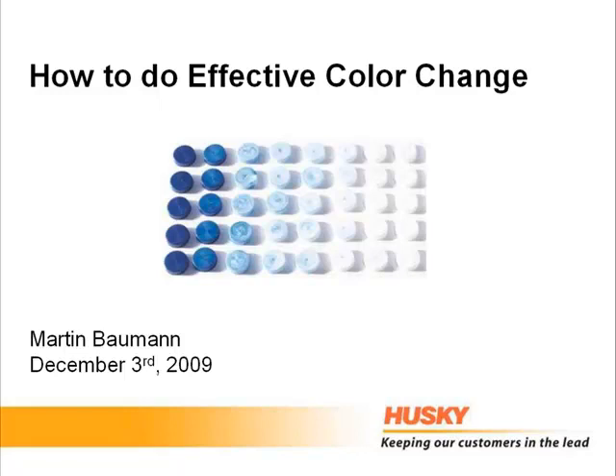One of the questions is actually if there's a difference in pressure drop with that mixing tip or the Ultraflow and a conventional tip, and the answer is it depends on the resin. Typically with polyolefins we haven't really seen it. We're now in our second generation with that mixing tip. We haven't seen a lot of pressure drop, but depending on the specific processing setup and the specific resin you use, it's always a good thing to check back with Husky if we actually foresee any problems. But otherwise, principally no issue.